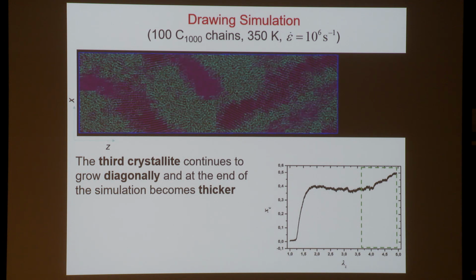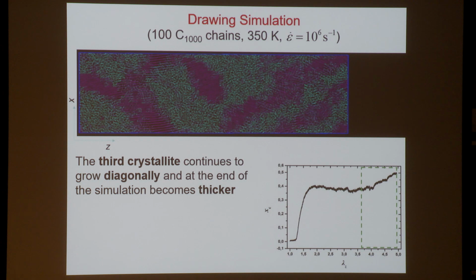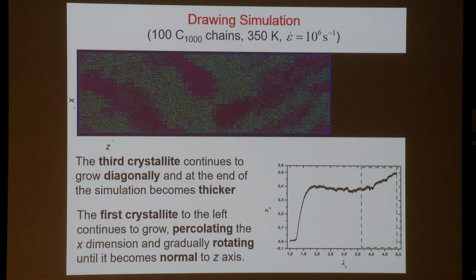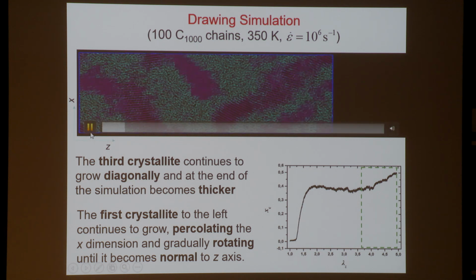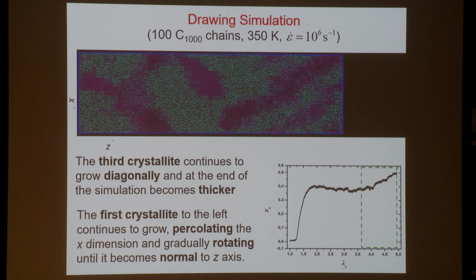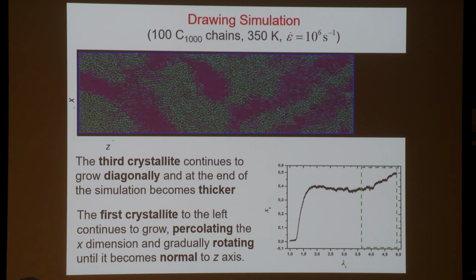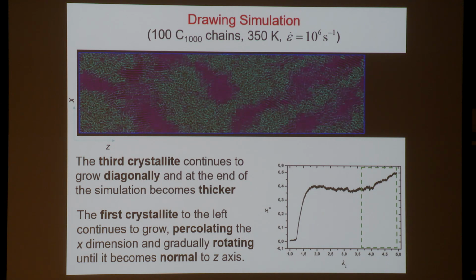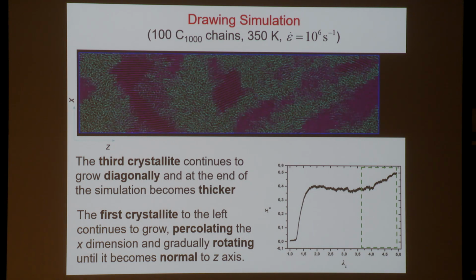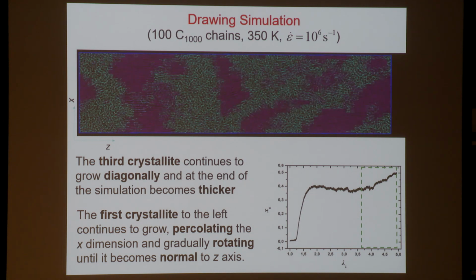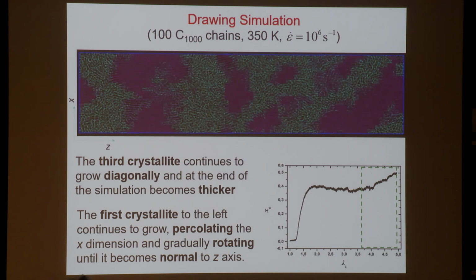Okay, so you see that ultimately there is a quite complex morphology that involves these crystalline regions dispersed in the amorphous region. And one could envision that through such simulations, having the morphology, one could calculate the tortuosity that such a structure would exhibit to a small molecule trying to go through the system, and therefore the permeability. Of course, it would be very advantageous if such calculations could be conducted in a coarse-grained sense to be able to look at smaller deformation rates and larger systems.